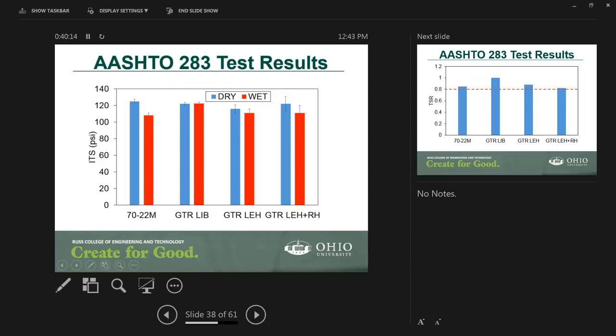The ITS for all mixes were greater than 100, as you can see, in all cases. What we have noticed is that the GTR mixes in general had very similar values, whether dry or wet, as compared to the polymer modified. The drop, again, with the 70 was higher as compared to the others, which is something that we have seen in the lab.